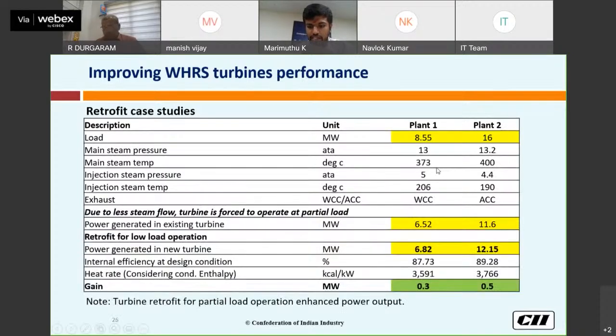And this is one case study based on retrofitting. You can see the figure for plant 1 and plant 2. It was designed for around 8.55 megawatt, but it had to operate at 6.52 due to low generation. Generally, if the load factor of the turbine is less, it reduces the efficiency. So to operate at low load, the turbine was retrofitted. With the same steam flow, which was generating 6.52, after retrofitting it gave around 6.82, so a gain of around 0.3 megawatt was achieved.